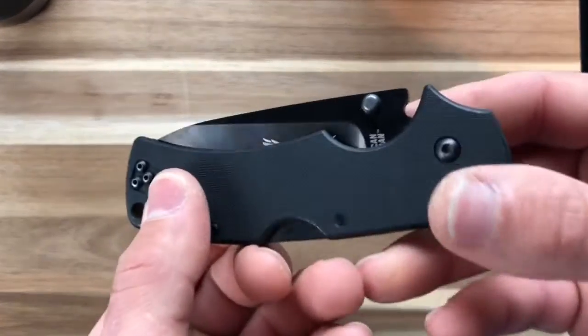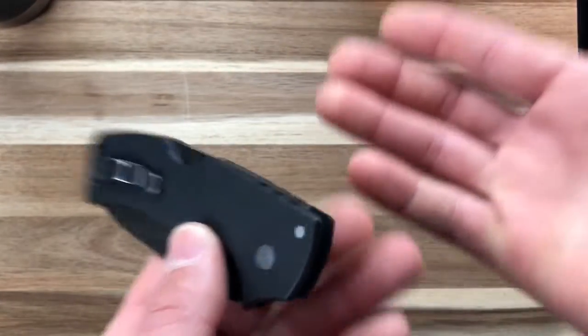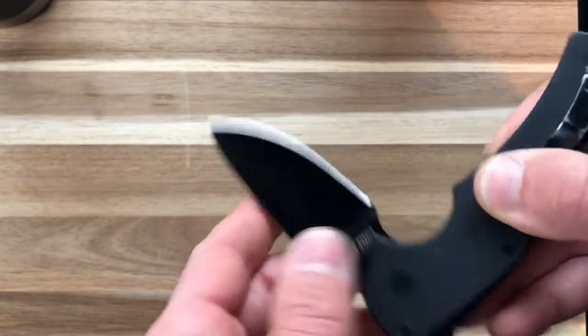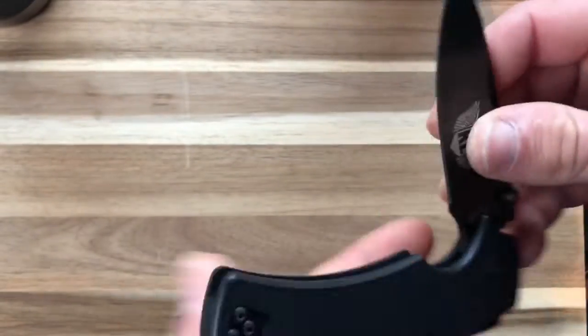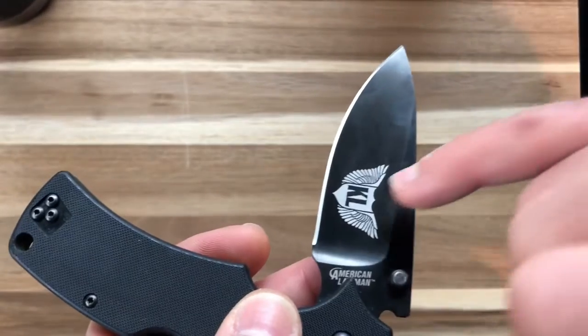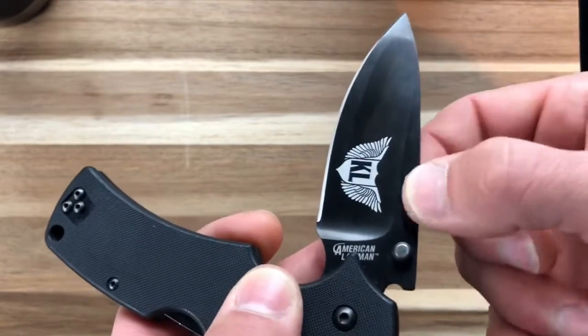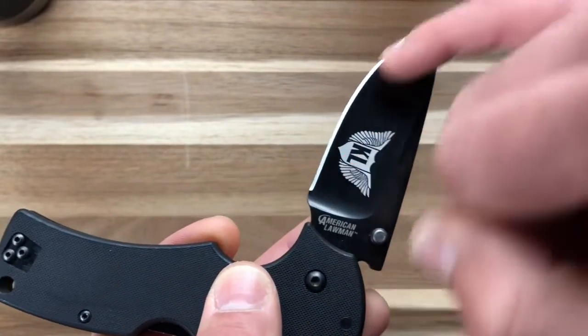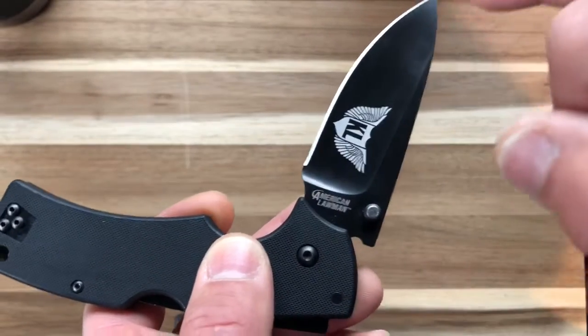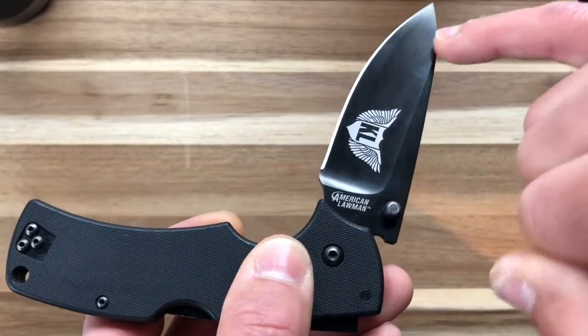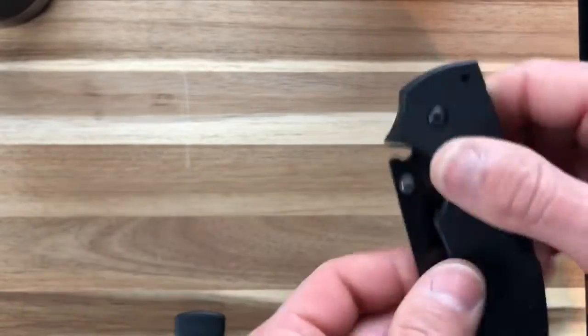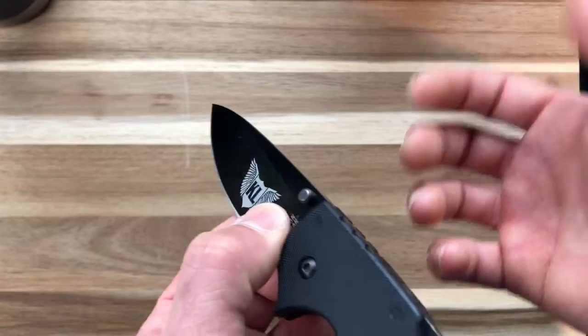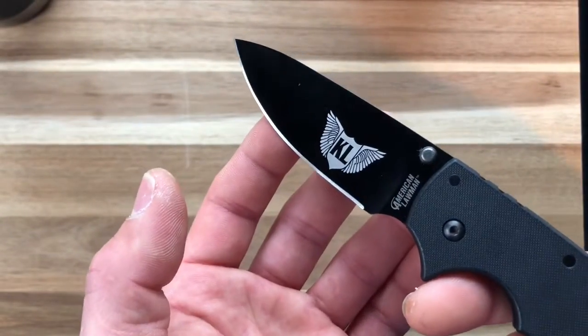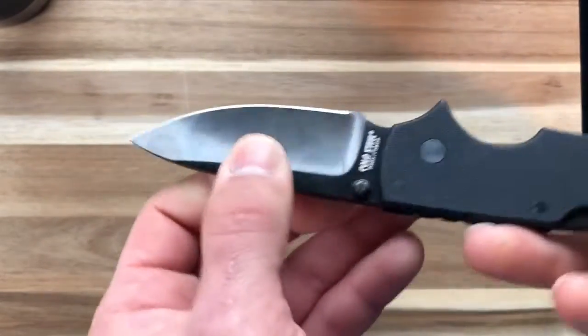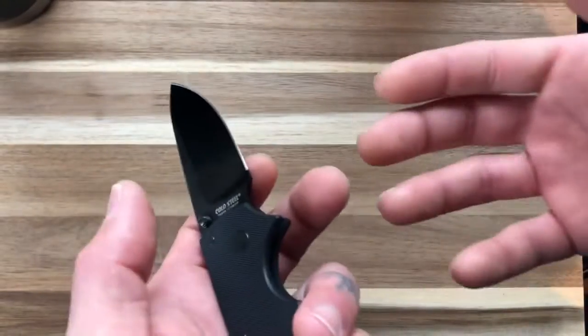It's not actually happening on these steels, because in a production world, you just can't do that. You got about 200 of these blades in a room at the same time being heat treated in the same room. There's no way you can heat treat this more than this. Also, they do the grinding on these blades after the heat treat, because in this type of production heat treating, you can't heat the edge up less than the spine. And if you're heating this whole blade up to the same temperature, but you don't have anything on the spine or the blade to protect it from getting too hot, you would have warping in the blade. So they don't grind this till after they're heat treated. So there's no way you would get a different HRC here than here unless it's actually a bad heat treat where it didn't properly distribute the carbides or the heat for that matter. So these blades are cut into a blank and then they're heat treated, and then they do the grinding afterwards.